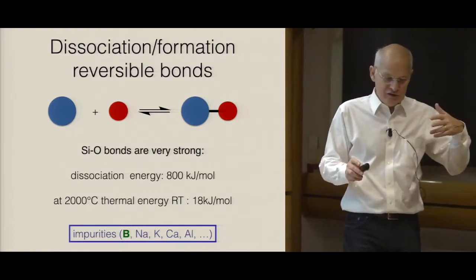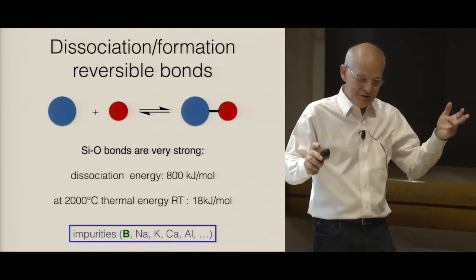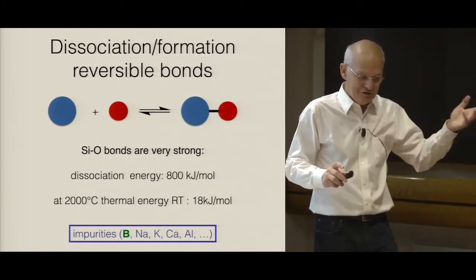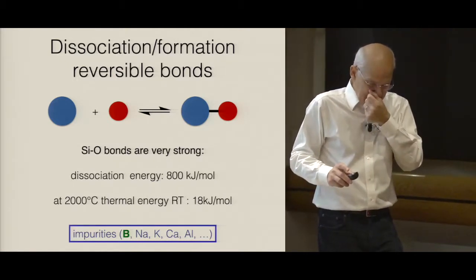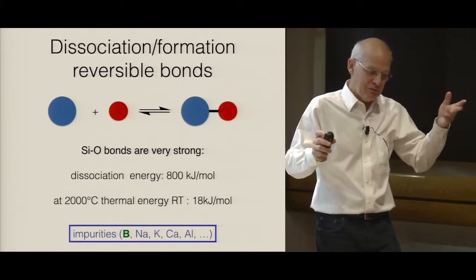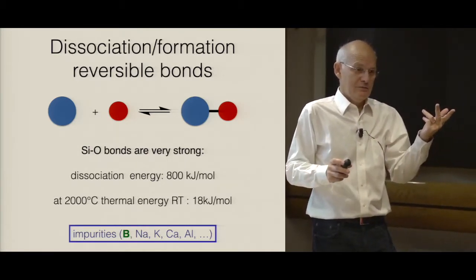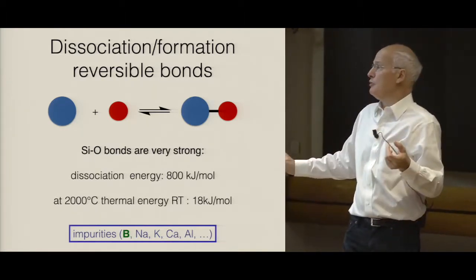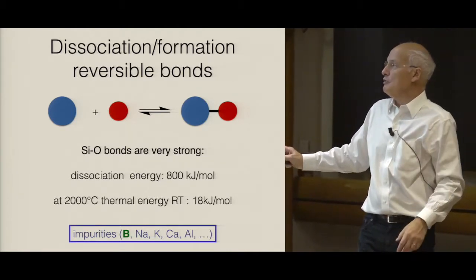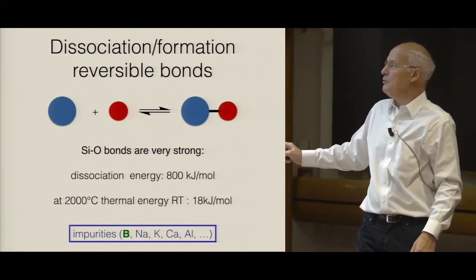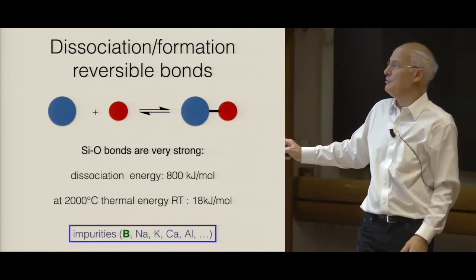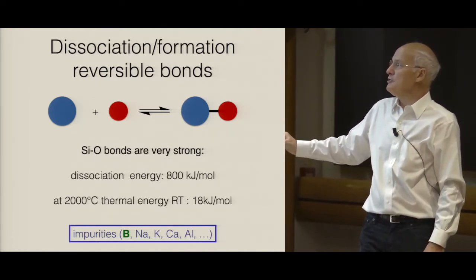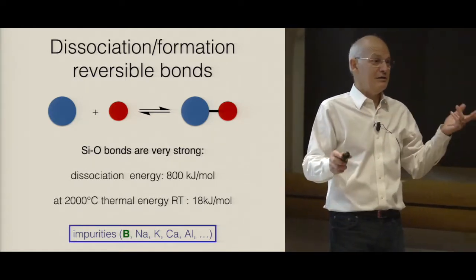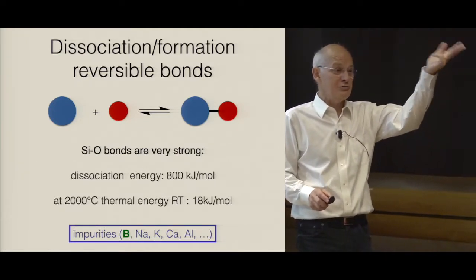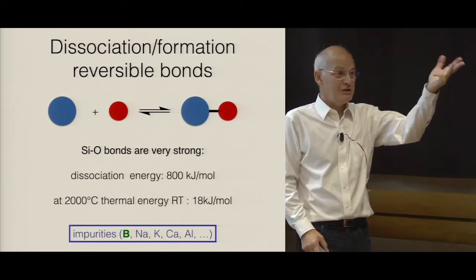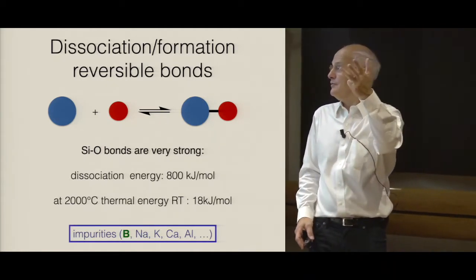When you look at these papers, published even this year, about how the stained glasses are made and what the transition is, you find that people say something and then they say, oh, but probably you break the bonds. But the silicon-oxygen bond is extremely strong. The energy of the bond is 800 kilojoules per mole. So if our mathematics is correct, at 2000 degrees the thermal energy is only 18 or maybe 20 kilojoules per mole, which means that the probability of breaking the bond is non-existent. You cannot break the bonds by heating silica to 2000 degrees. So the question is, what makes the system flow.